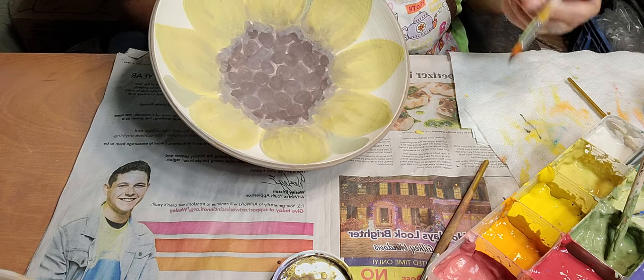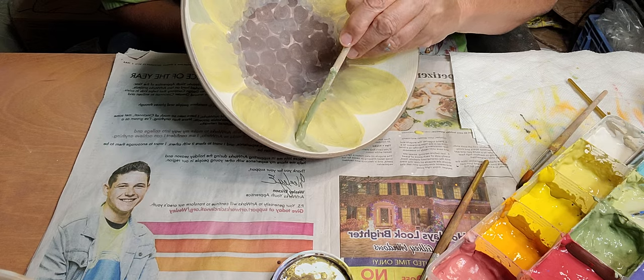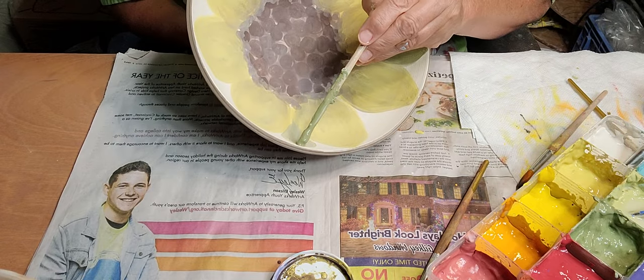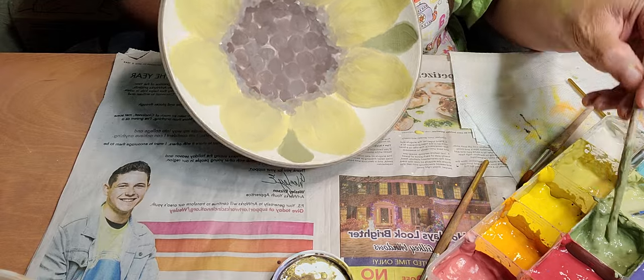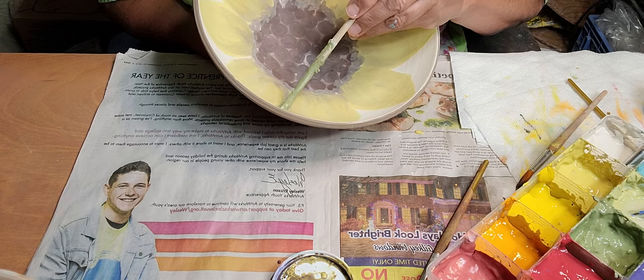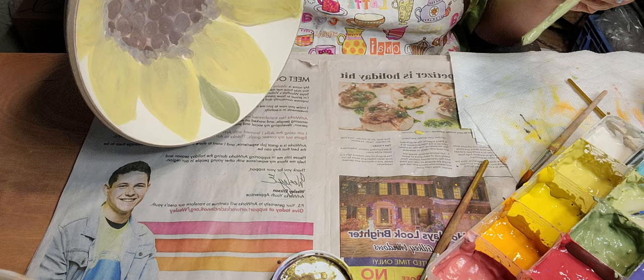I'm going to go over the leaves again because green has a tendency to burn out brown at this high temperature. Like I said, if it were low fire the colors are always a little bit brighter, but at high fire they burn out a little bit.